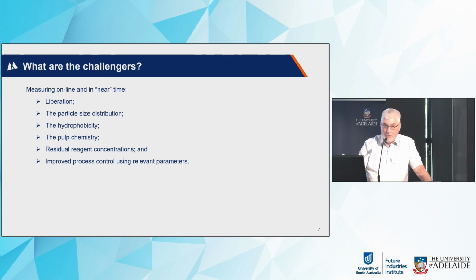A lot of PSI or particle size monitors, they measure a single point. It's either a P80 or a P50 or a P something. We very rarely look at the size distribution. If you could measure a distribution, that might actually tell us something useful, and we could use that distribution to try and operate the plant better. If we could measure the hydrophobicity, it would give us an idea of actually have we conditioned the particles we want to separate correctly so that they will attach to a bubble.